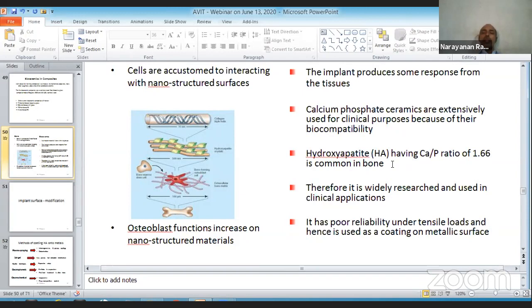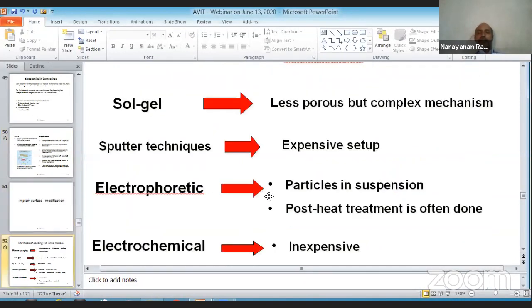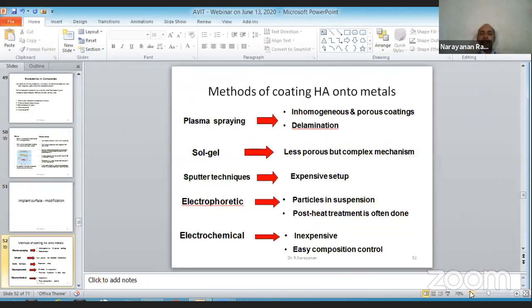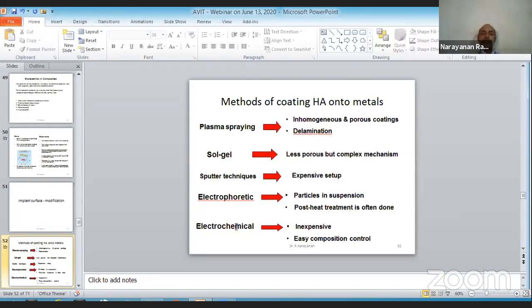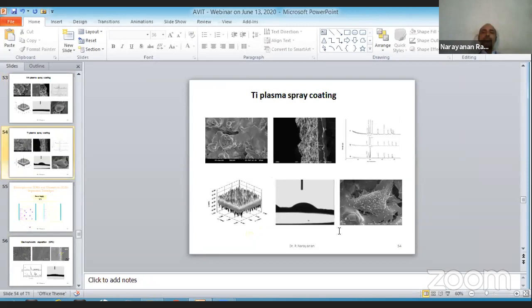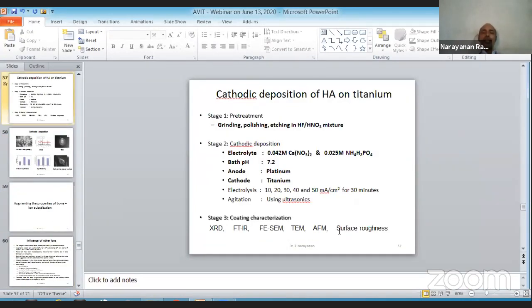So when you coat your titanium implant or stainless steel implant with hydroxyapatite, then the cells will attach easily. Since natural bone consists of this, if I can have a titanium metal with this, when this is placed inside the body in the vicinity of the bone, then the bone cells, the osteoblast cells, will easily attach to the implant. So with this idea, we try to produce a titanium implant surface with electrochemically formed hydroxyapatite. There are many techniques available, but we are interested only in this. So on a titanium implant surface, a hydroxyapatite coating was made by a very simple, inexpensive lab level cathodic deposition.